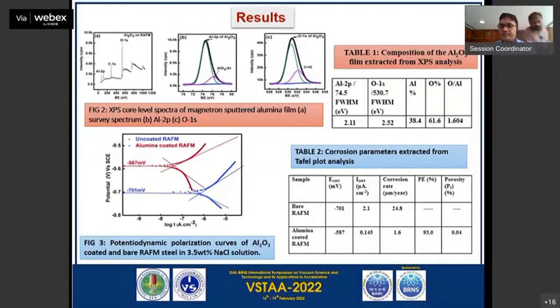So from the chart, you can see that the coating was very compact in nature because the porosity was 0.04%, and the protective efficiency against the medium was 93%. And the corrosion rate also, you can see that the alumina coated substrate got 1.6 micron per year as compared to the bare substrate at 24.8 micron per year.